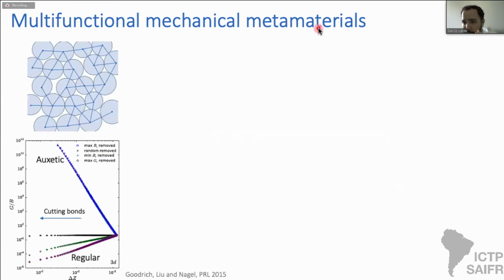Now, some people at Penn and Chicago developed this very interesting idea that you could cut bonds of a disordered lattice to control whether this material exhibits auxetic response or not. Depending on the protocol you use to cut the bonds, the ratio between the shear and the bulk moduli can go up, as it happens for an auxetic, or down, as is the case for our regular material.